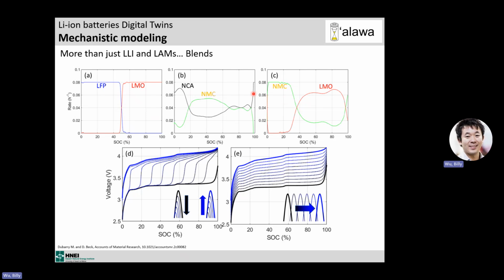And that affects a little bit the voltage response of the cell. So in our model, we can adjust that, and we just proved it recently, and we published a paper in Batteries where we showcase that at low rate, we have a big impact. But for faster rate, it might have an impact too. So if you want to diagnose the cell on a blend, you might want to take that into consideration.